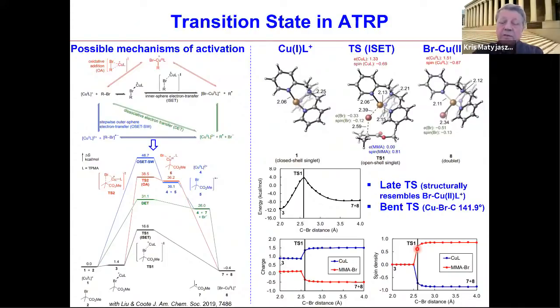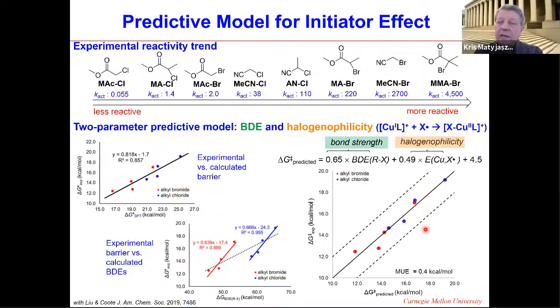There are two components to atom transfer. One is the alkyl halide, the other is the copper complex. The alkyl halides shown here differ in reactivity by a factor of 100,000. In fact, we have some alkyl halide initiators which are an additional 40,000 times more active. So that is a tremendous difference. You could think that the bond dissociation energy between carbon and halogen would be most important. In fact, it is important, but not only.